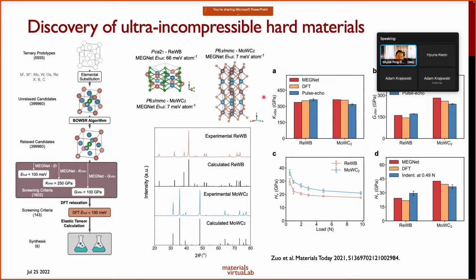And Professor Luo's group also did pulse echo measurements of things like the bulk modulus and shear modulus as well as hardness. And again, what you see is that the machine learning model predictions as well as the DFT as well as the pulse echo measurements are in very, very good agreement with one another, right? So this just shows you the power when you start all the way from a machine learning model. You now can play with a much bigger space of structures. Instead of doing most typical DFT screening works where you have maybe up to 1,000 materials or maybe a few thousand materials, you can start with 400,000 materials. You can even start with 1 million materials, and you can screen things very quickly to identify good potential candidates before you actually do your DFT calculations. Okay.